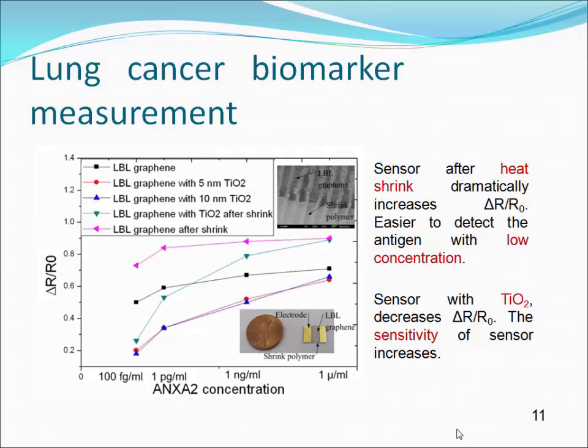also increases. The layer-by-layer graphene's response is this black curve, and the layer-by-layer graphene after heat shrink is this pink curve. We can see clearly that after heat shrink, our sensor signal increases dramatically, or the resistance shift increases. I think this is because the heat shrink introduced small structures, enlarges the surface area of the film, and it's easier for us to detect the antigen with low concentration in this way.